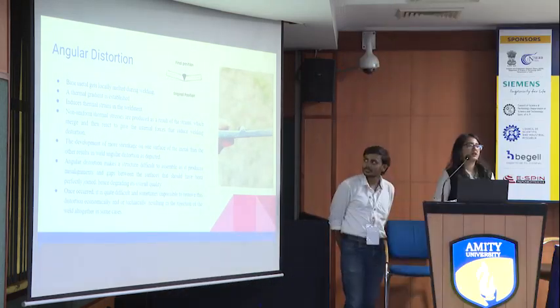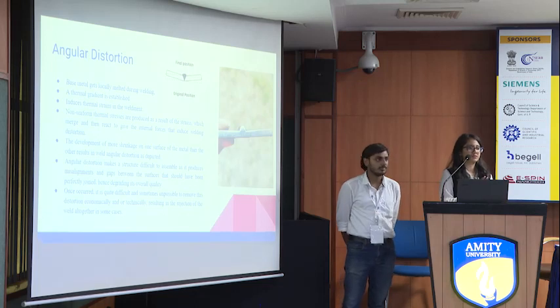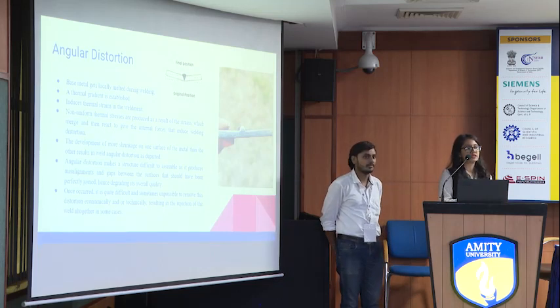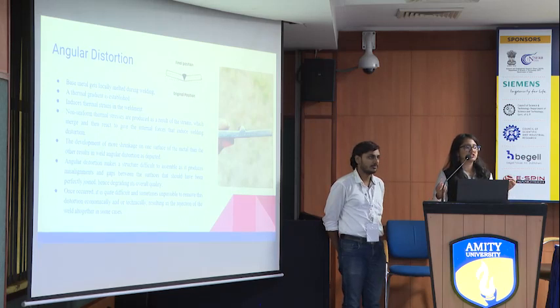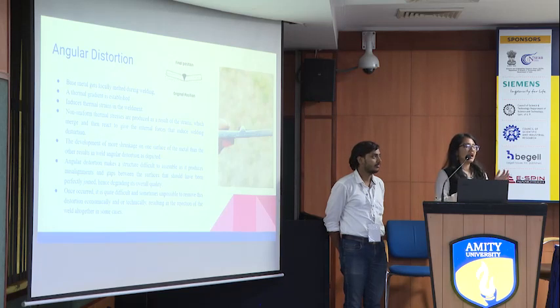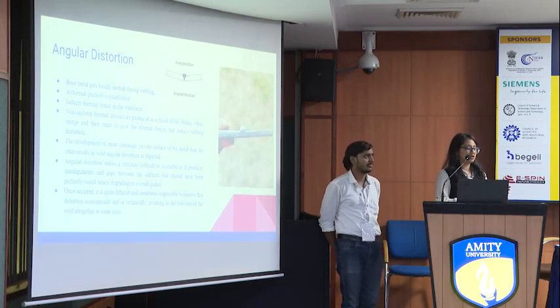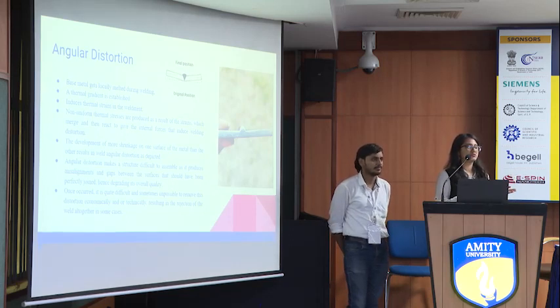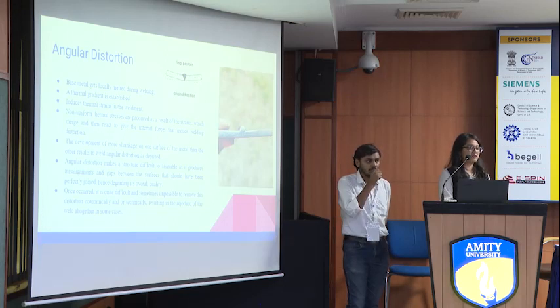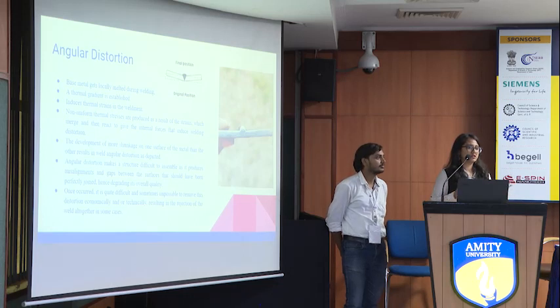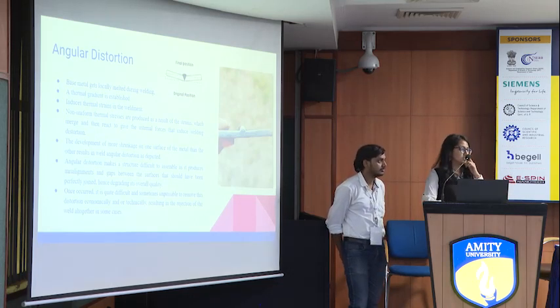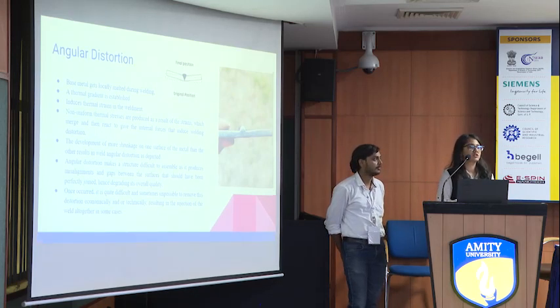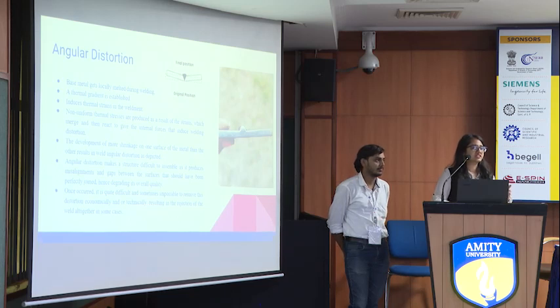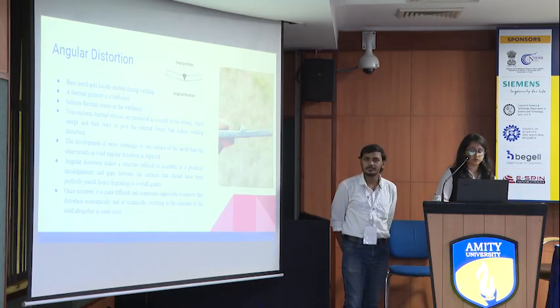So coming to angular distortion, when we weld a plate or any base material, the point where the welding is taking place has a high heat, but at the ends of the plate, the heat concentration is low, thereby making a heat gradient, and when the heat is cooling down, the cooling rate differs because of the heat gradient, which makes the contraction at the center more than at the corner of the plate, which leads to angular distortion. Angular distortion is very catastrophic, as if we do not treat this angular distortion, it can lead to high stresses in pressure vessels or any steel that we are using, even in the automobile sector.